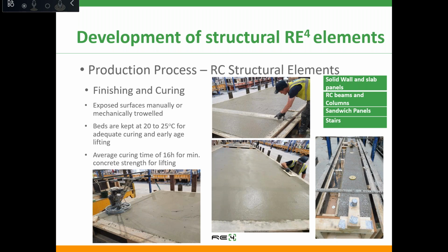The panels then are left to cure in the factory on the heated tables for approximately 16 hours before the next stage. We try to keep the bed at 20 to 25 degrees, which we found is the most accurate temperature to cure the concrete and achieve the requirement of 15 megapascals for lifting. You can see there are some pictures of the guys finishing the wall panels and sandwich panels on site, and on the right you can see one of the beams already cast in the mold.